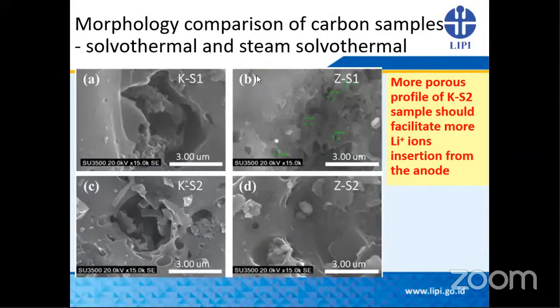And we also compared the morphology between the solvothermal and steam solvothermal methods using two kinds of solvent, which are potassium hydroxide and zinc chloride. K is potassium hydroxide, S1 is conventional solvothermal, while Z is zinc chloride, and S2 is steam solvothermal. So we can see here the more porous profile of the KS2 sample. It should facilitate more lithium ion insertion from the anode. So we consider this kind of carbon sample is better than the other samples.